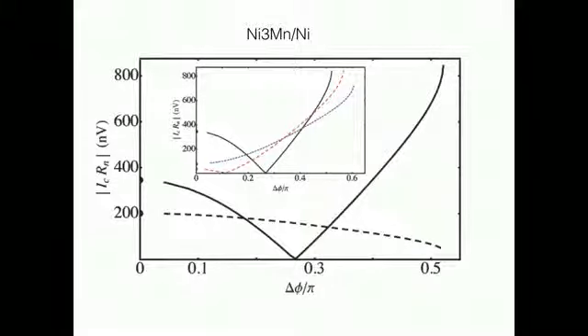Further, the zero-pi transition, presented in a paper on the spin valve by Houzet and Buzdin, cannot apply here either since the singlet contribution is negligible in a spin valve system of similar thickness. What we see here is a new type of zero-pi transition.